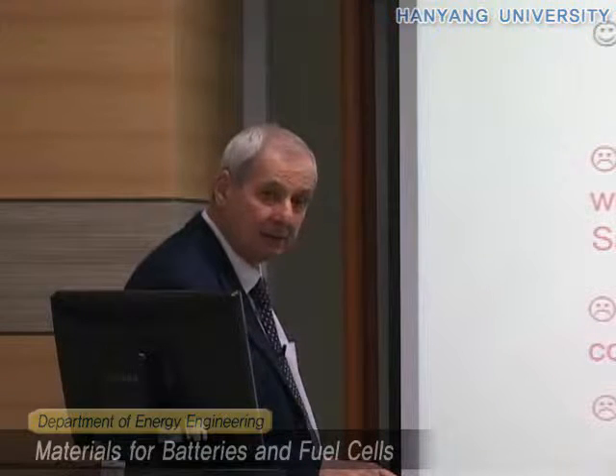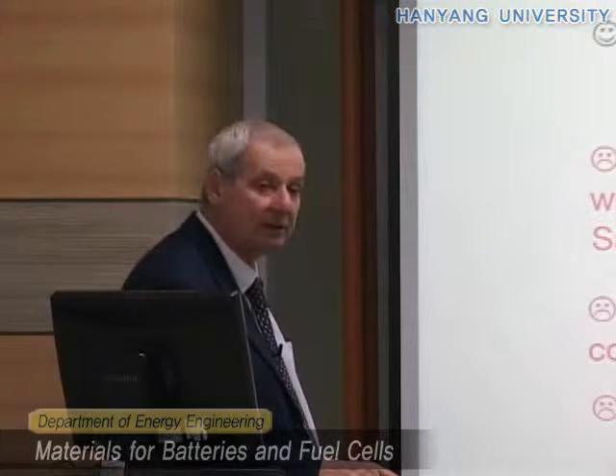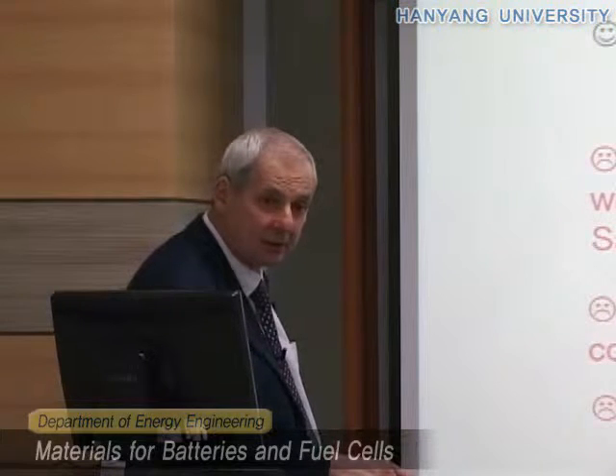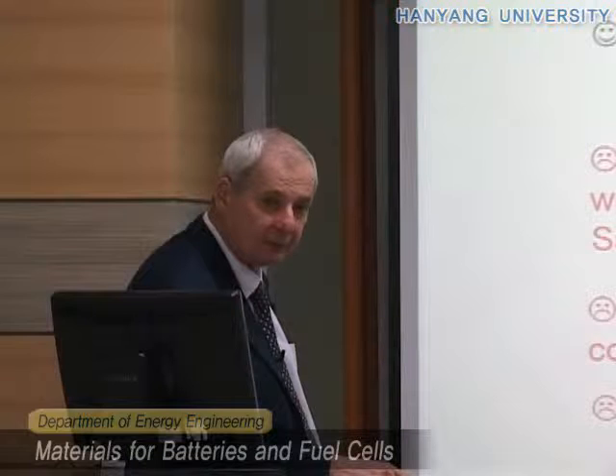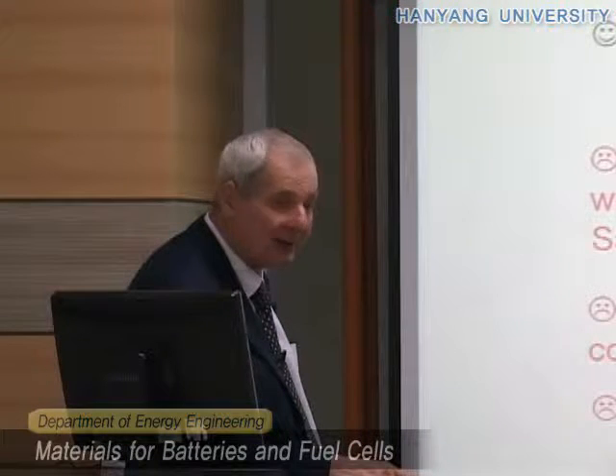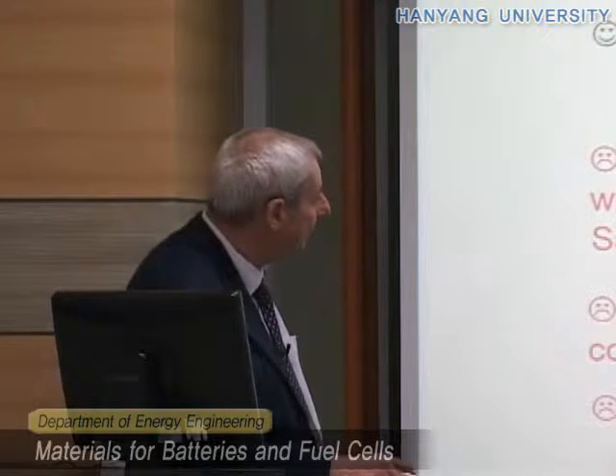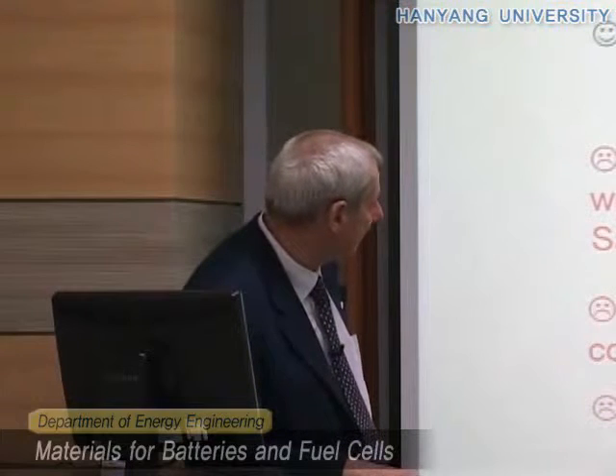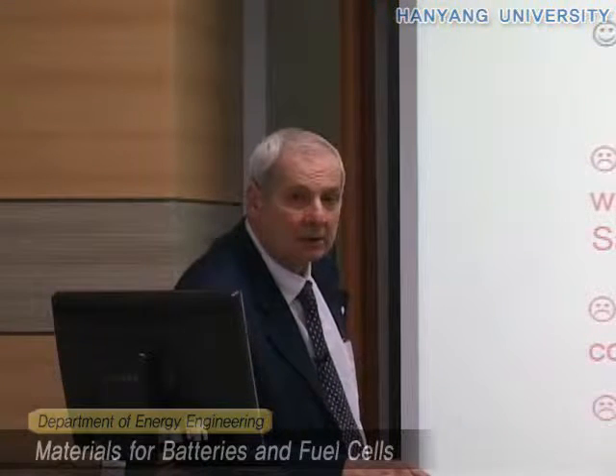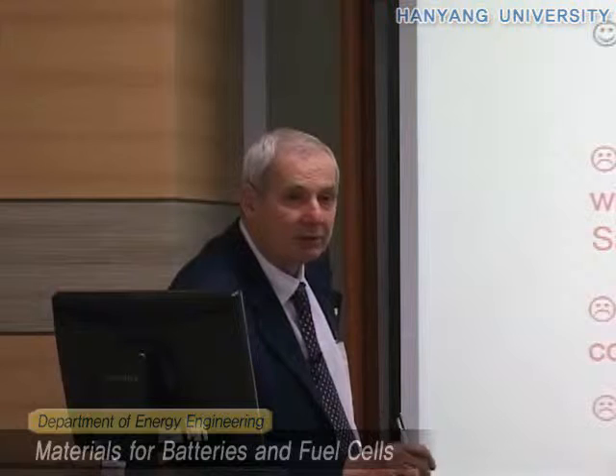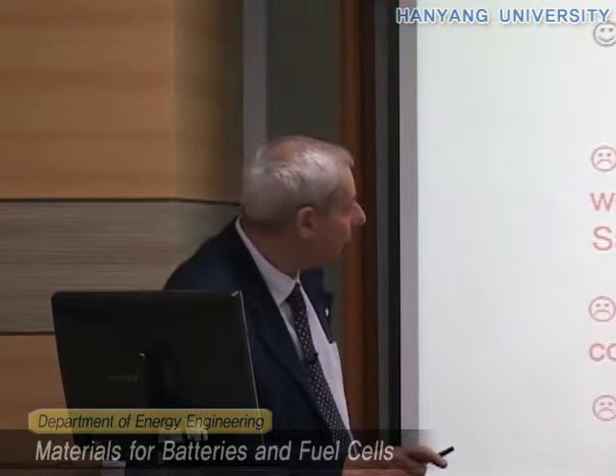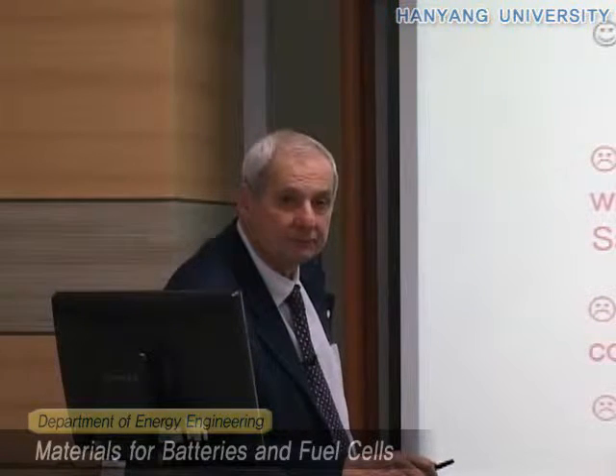And this is bad, because if they get some water, there is a reaction with the LiPF6, with the formation of HF, which destroys the battery. So you must be very careful when you handle this electrolyte. In the laboratory, you have to use a dry box. In the production of the battery, you have to use dry rooms.